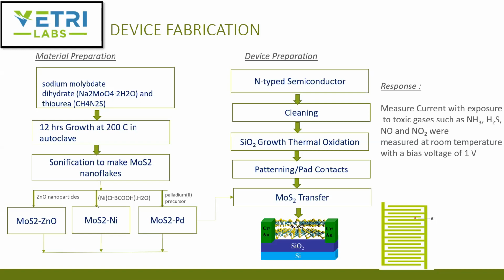First, obviously, you clean the semiconductor, and you're putting the material on a silicon wafer. So you're growing silicon oxide using a thermal oxidation process. Then you put pad contacts using patterning, which is photoresist and the typical semiconductor process. You put chromium and gold pad contacts, and then the MoS2 material, either functionalized or just MoS2, is transferred to form the structure shown here. In a Z direction or an XY direction, the current collector is shown, which ties that moly sulfide functionalized material onto that wafer.